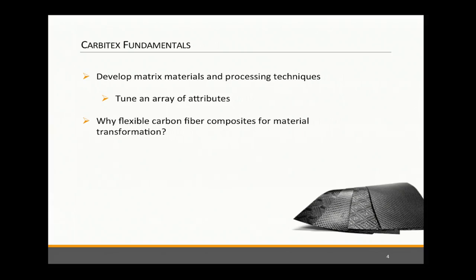So really, what's the difference between a traditional carbon composite and a flexible one? Essentially, flexible carbon fiber technology is unlike traditional carbon fiber composites that are limited in the bending radii for very thin laminate layers, where exceeding that bend radius results in resin and fiber breakage. So the key to our material and our technology is the very low shear modulus that allows compliance at the interface between the fiber and the resin. And this low shear modulus with a high elongation relieves the cracking and bending failures in traditional carbon fiber composites.